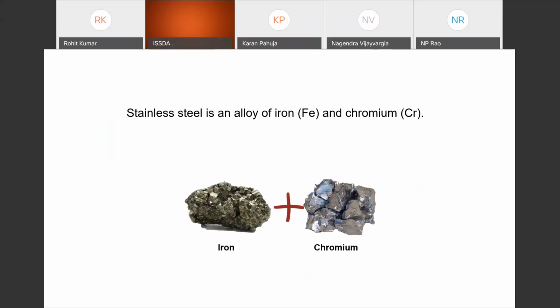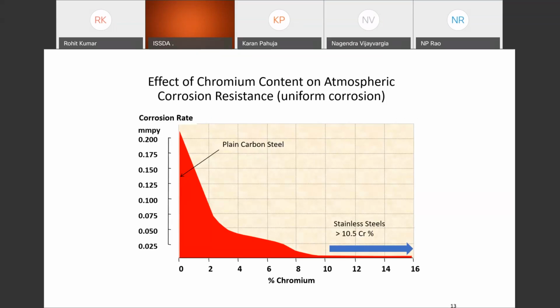Stainless steel is generally understood to be an alloy of chromium, nickel, molybdenum, and other materials. But to make basic stainless steel, you have to just add chromium into iron. If you look at this graph on the left-hand side, there is the corrosion rate, and on the x-axis it is chromium percentage. If you keep increasing chromium in iron, 2%, 4%, 6%, 8%, but when you reach a minimum of 10.5%, suddenly it stops corroding like carbon steel.